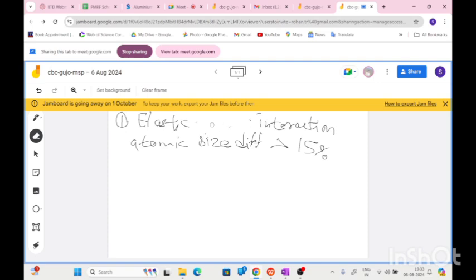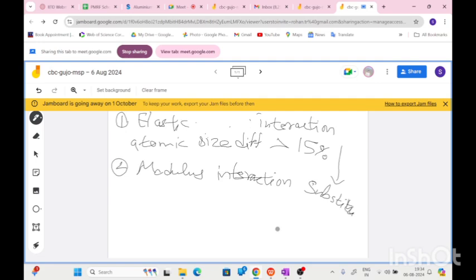First is the elastic interaction, second is the modulus interaction. In the elastic interaction, the substitutional atoms will impose compressive stress on the dislocation. And if we see the interstitial atom,